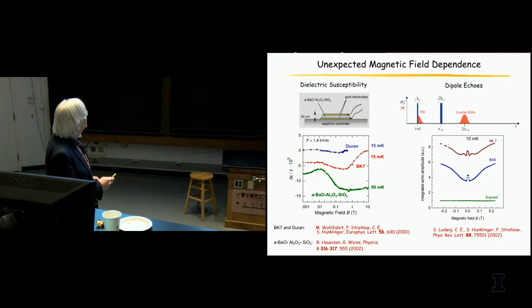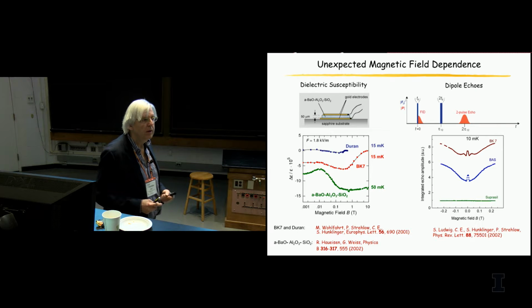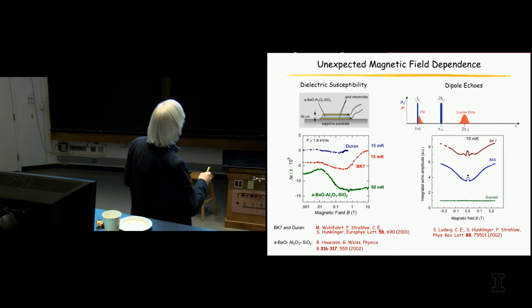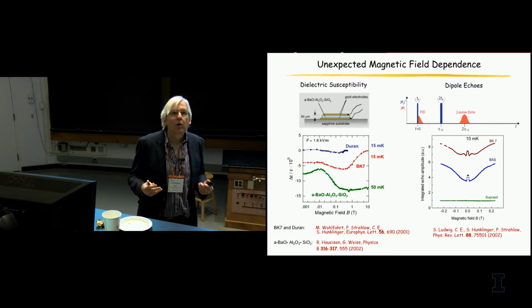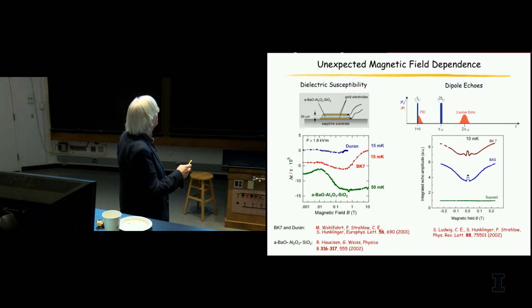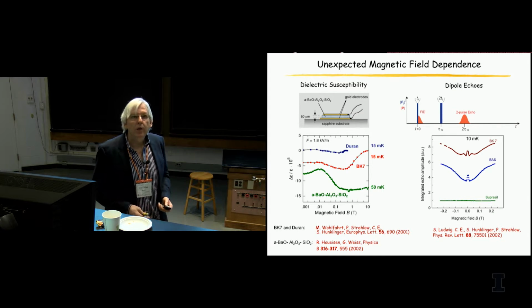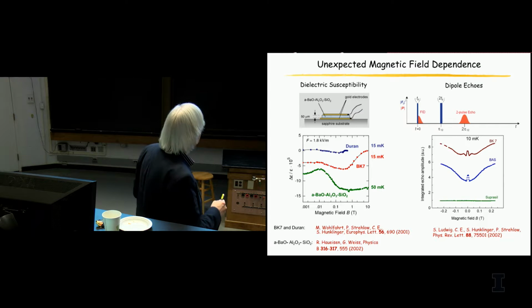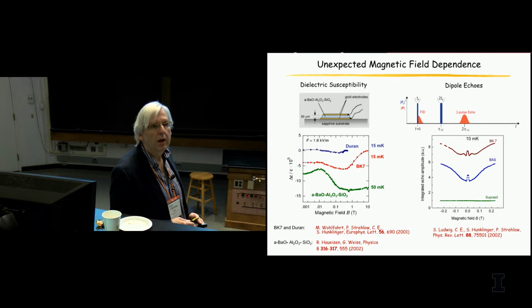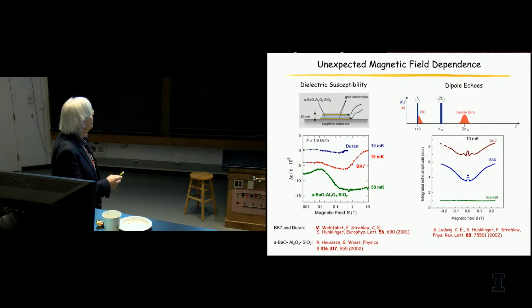On the other hand, later on, echoes were done, microwave echoes. So you have 2 pulses, like an NMR echo, and you get a microwave pulse out of the sample. And the question there was, if I do this experiment in a magnetic field, what would happen? And you can see here 3 different glasses.